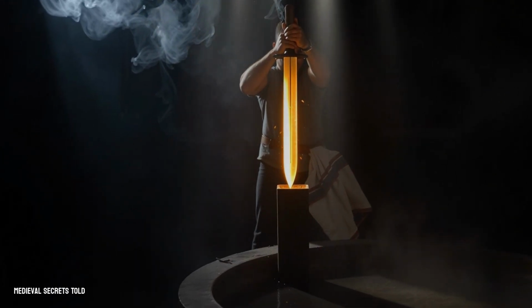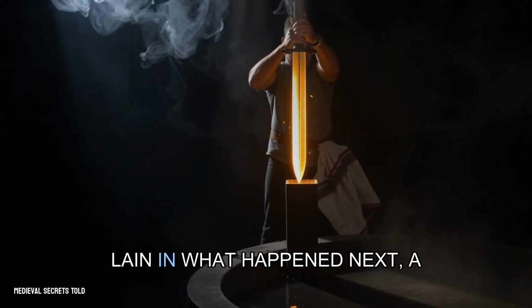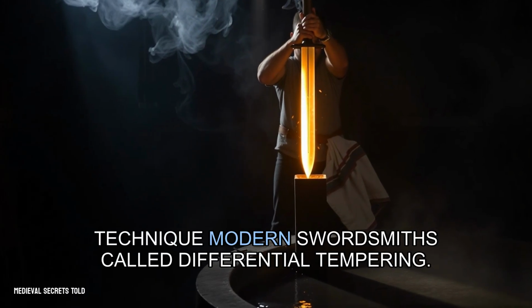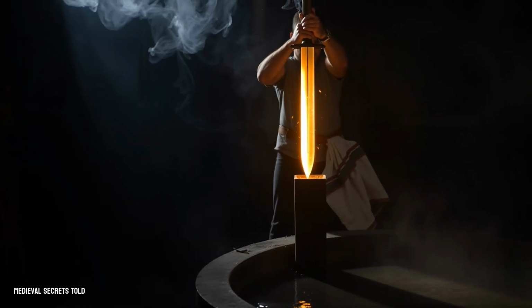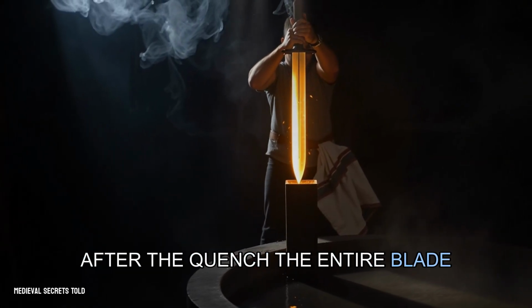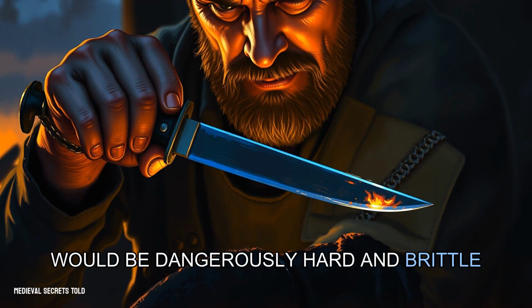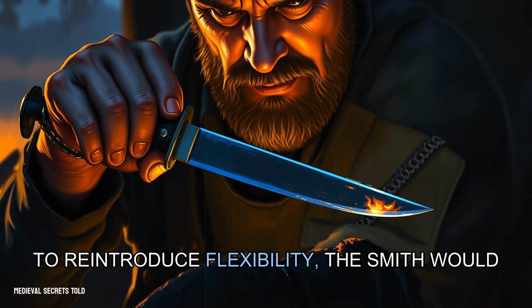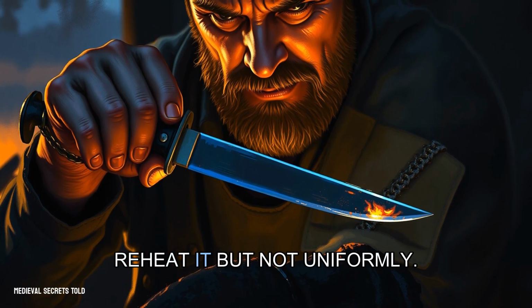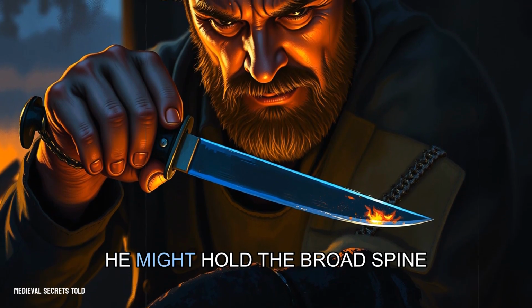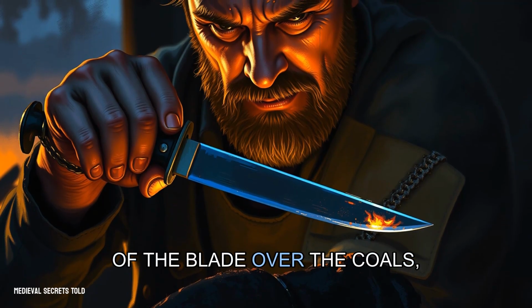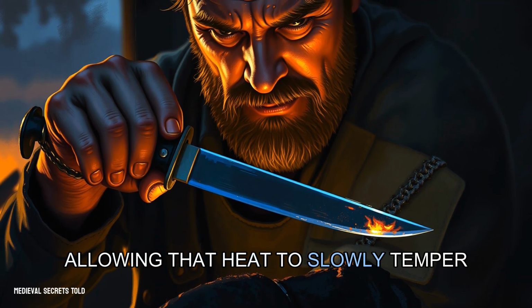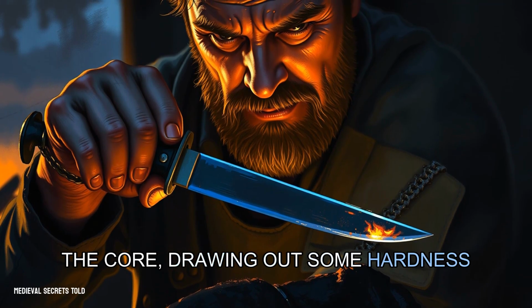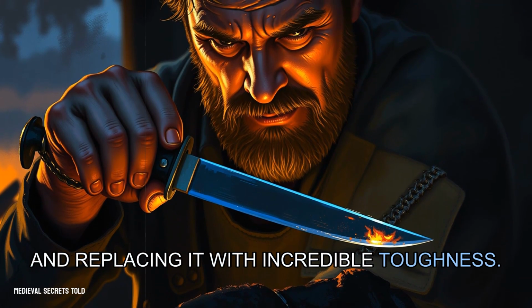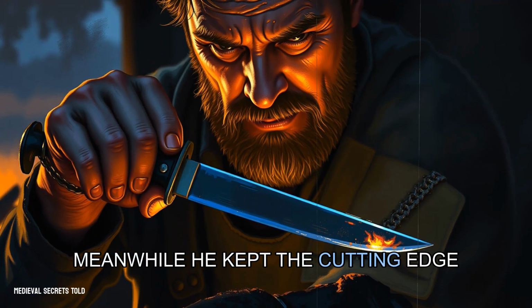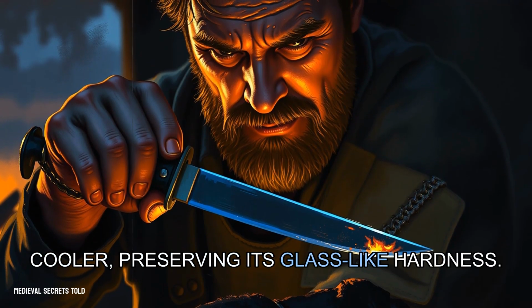of failure. But the true genius may have lain in what happened next, a technique modern swordsmiths call differential tempering. After the quench, the entire blade would be dangerously hard and brittle like glass. To reintroduce flexibility, the smith would reheat it, but not uniformly. He might hold the broad spine of the blade over the coals, allowing that heat to slowly temper the core, drawing out some hardness and replacing it with incredible toughness. Meanwhile, he kept the cutting edge cooler, preserving its glass-like hardness.